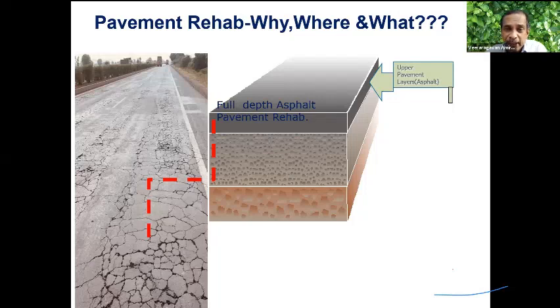For sustainable pavement, I am rejuvenating the old pavement, which is deteriorated. I am adding only maybe 10% virgin material. I can use the whole bitumen layer, which may be 3% binder, 3.5% binder. I had to add only 1 to 1.5% binder. So I am reducing the cost. I am rejuvenating the pavement layers. I am improving the performance.